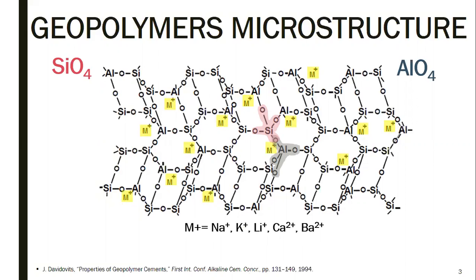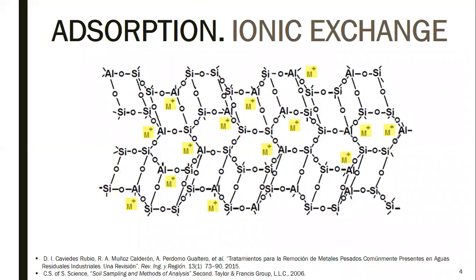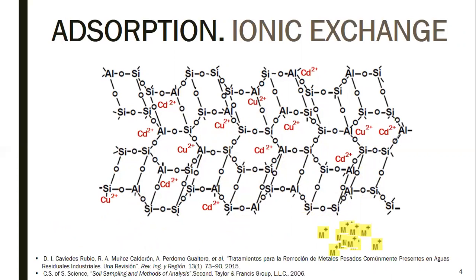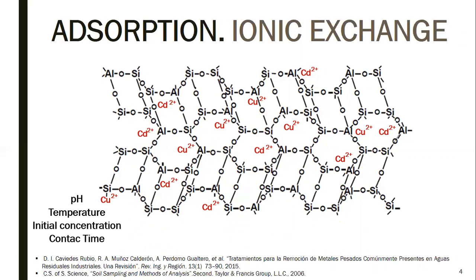The network that constitutes these materials is negatively charged due to aluminum being linked to four oxygens. This charge is compensated by cations that are trapped in the intracrystalline spaces. These ions are easily interchangeable, and this peculiarity gives the geopolymer the ability to attract heavy metal ions. These characteristics are mainly affected by the change of pH, temperature, initial concentration, and contact time.